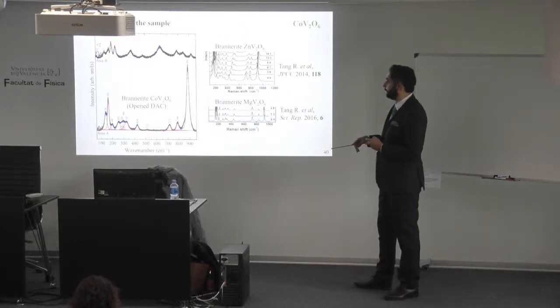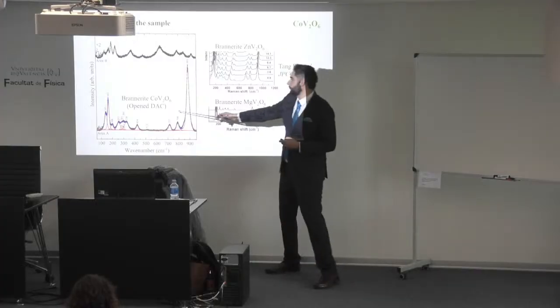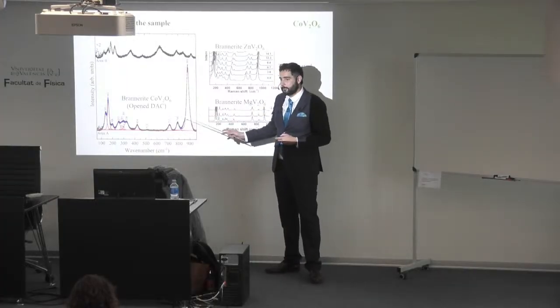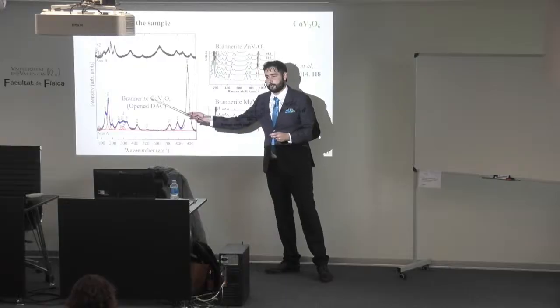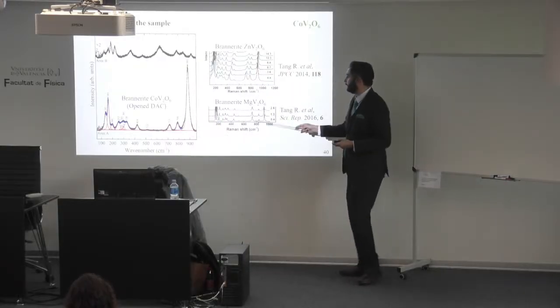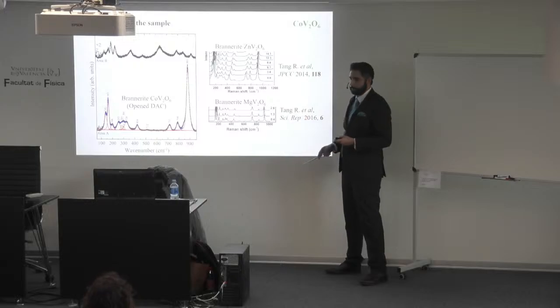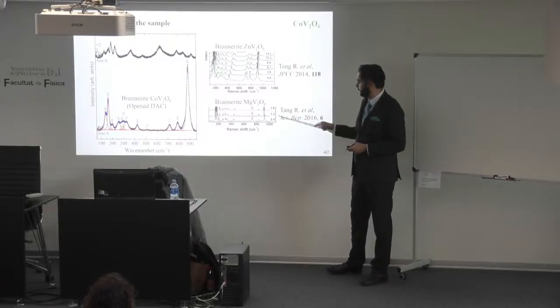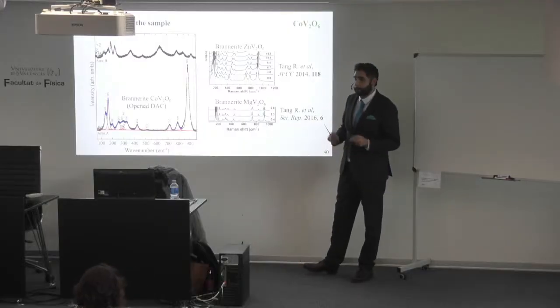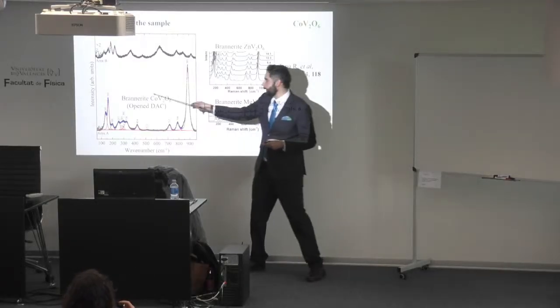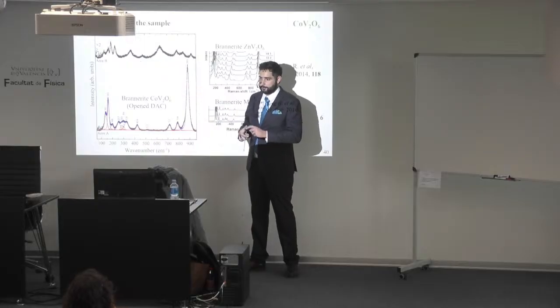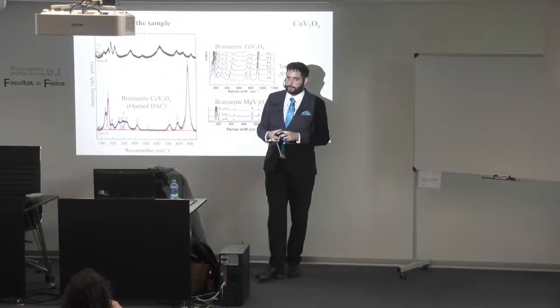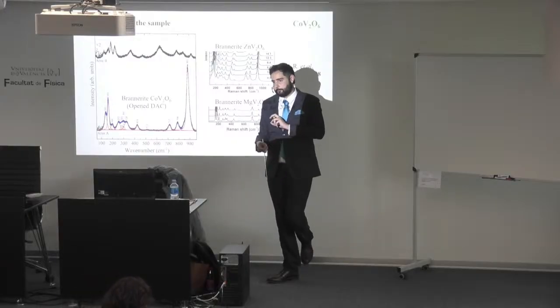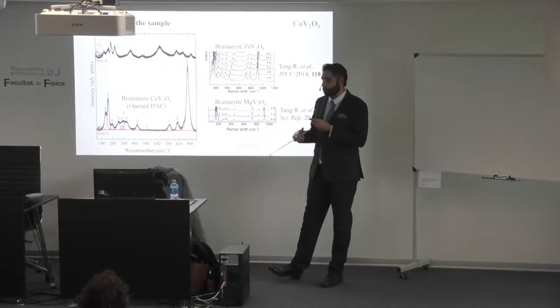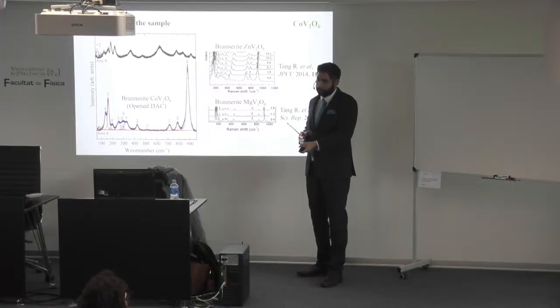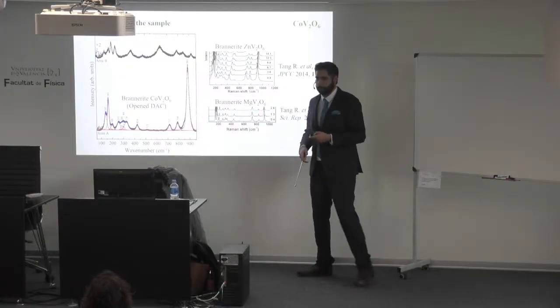But as we went back in pressure, when we opened the diamond anvil cell and performed the Raman, we perfectly see the brannerite signal. This is not reported, so if we compare it with zinc metavanadate and magnesium metavanadate in the brannerite structure, the profile is exactly the same. But not all the sample went back to brannerite. We had other places where the sample had a different signal. We did this with a single crystal, so it got polycrystals inside. So we don't know exactly how the mechanism of reverting works, but at least we got the brannerite signal.